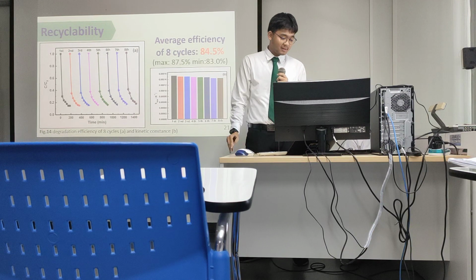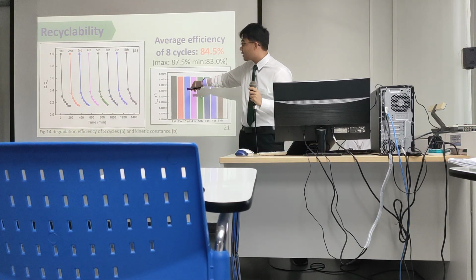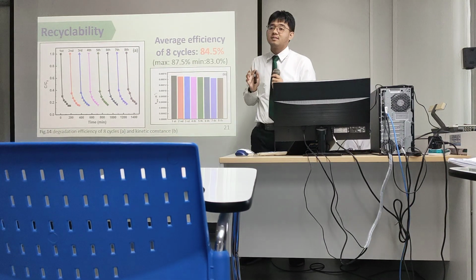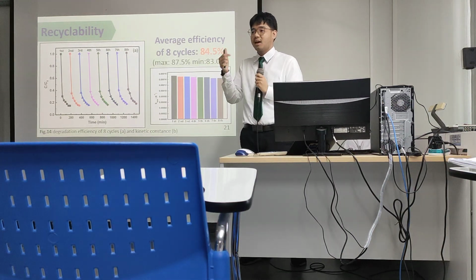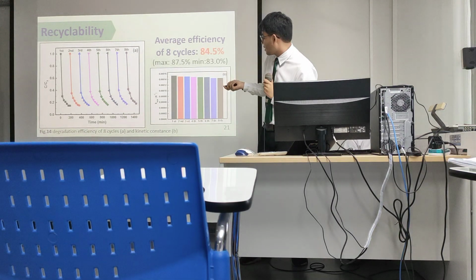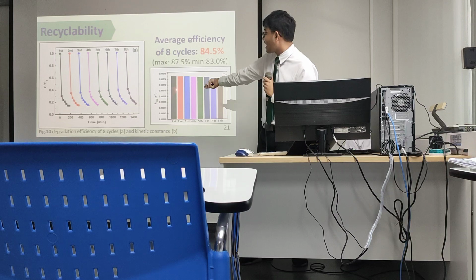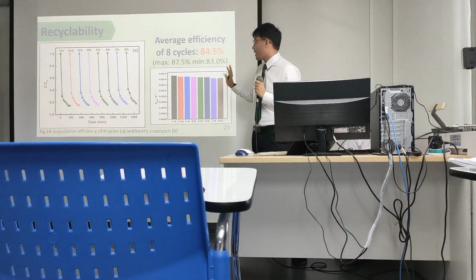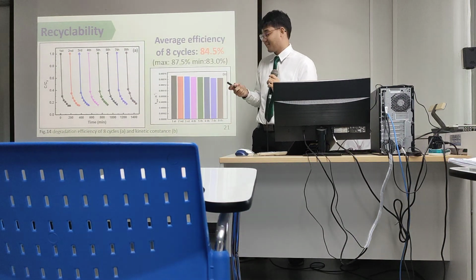Recyclability. You can see it is slightly decreased, and it's because of material leaching, heavy metal leaching. And this is the kinetic constant. It's decreasing too, for the same reason.